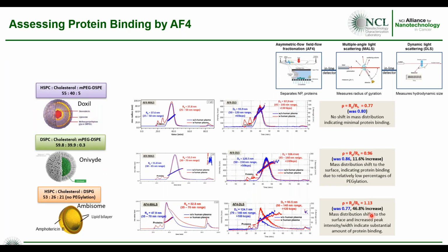And this is expected because there is no PEG on the surface. Moreover, if you look at these fractograms, you don't need to calculate this shape factor to see that something is going on. The peak shown in red is much broader after incubation with the human plasma, signifying that there is some binding to the surface.